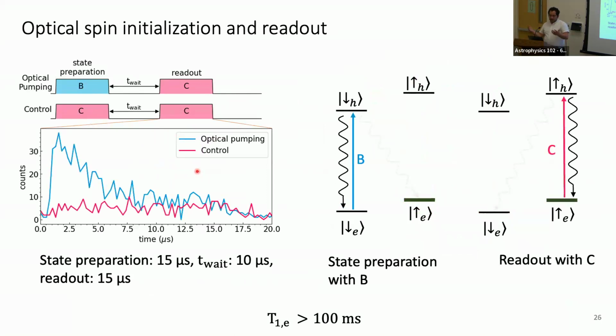This is some example data showing this time scale. We can optically polarize these spins by pumping and use the same mechanism to read out. Just by this incoherent mechanism, we can already characterize T1. We measured it up to 100 milliseconds, so the spin polarization is longer than 100 milliseconds. Beyond that, we just stopped measuring. So the T1 time is very good, and that's what we expect based on the electronic structure.